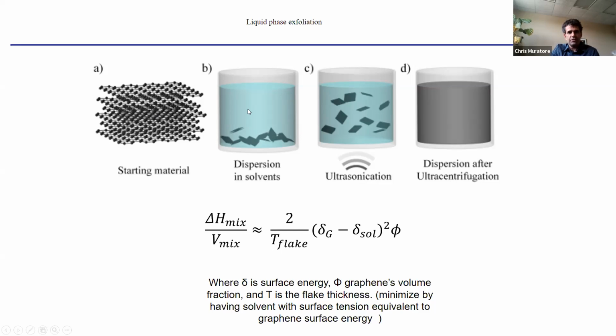You immerse it in some solvent and you introduce some energy. Typically sonication is the form of energy. And through cavitation and other processes, maybe some chemistry with the solvent, depending on what you're using, you can break this crystal apart. So you can introduce the energy as an alternative to the mechanical energy for cleaving this crystal. This sonication energy can break the material apart.